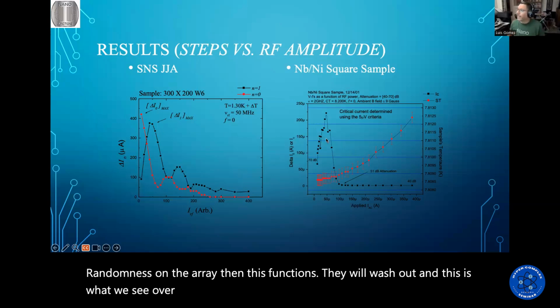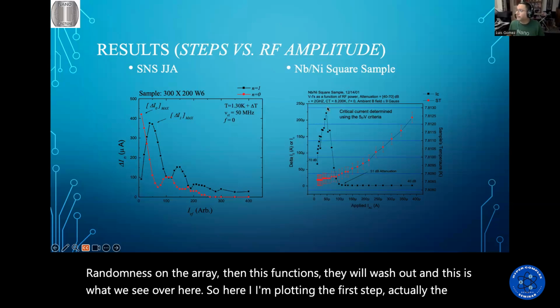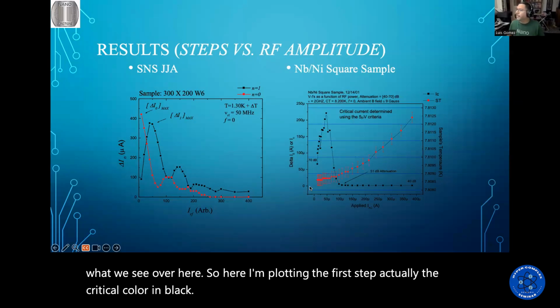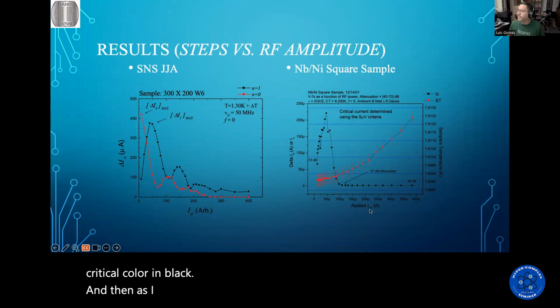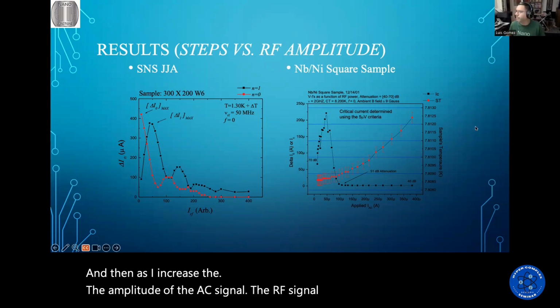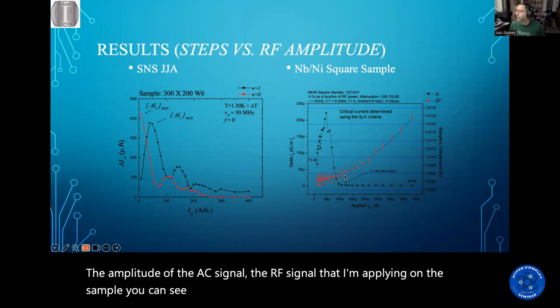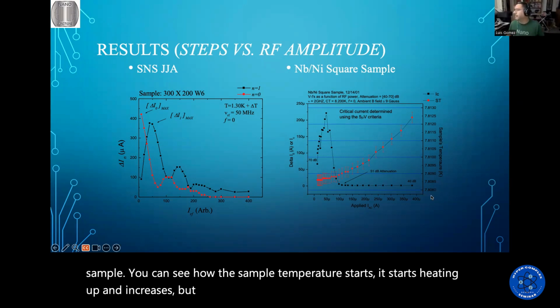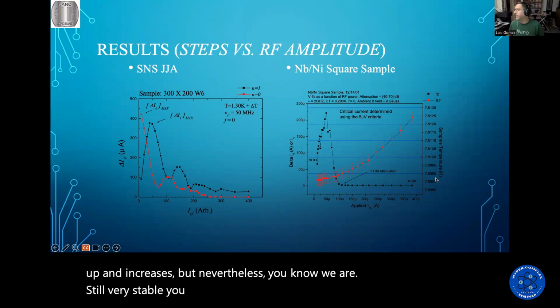So here I'm plotting the first step, the critical current, in black. As I increase the amplitude of the AC signal, the RF signal applied on the sample, you can see how the sample temperature starts heating up and increases. Nevertheless, we are still very stable, even though there is some heating effect.